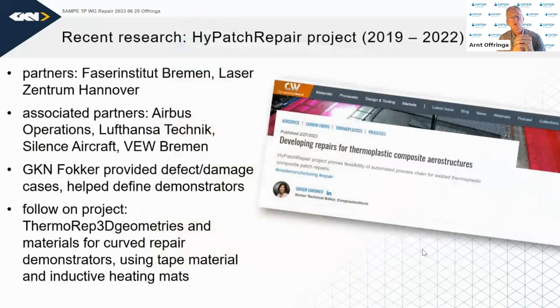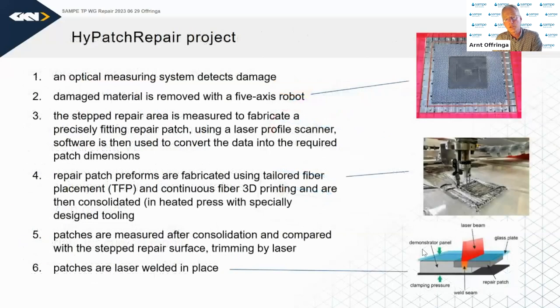And similar work was also done extensively recently by the Fiber Institute in Bremen and the Laser Center Hanover, and it's also published in Composites World. Together with Airbus Operations and Lufthansa Technik, they looked to see if you can create a repair area with an exact geometry, so a recess in the product where you put a patch, and the patch is specifically designed and made to fit exactly into the recess, and then using welding, you put the patch in position. So here are some pictures from that research.